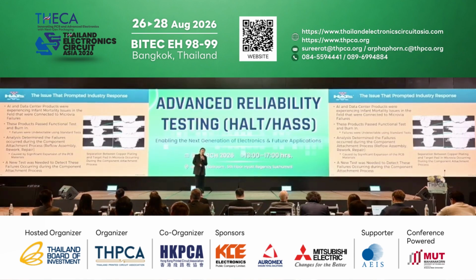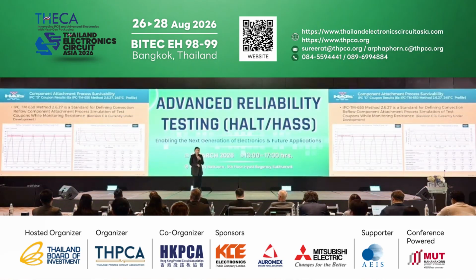After all the failure analysis research, the experts realized that we need to do something to monitor what's going on in the real assembly process. So the experts and the IPC committees came up with a test method, IPC TM650 test method 2.6.27.